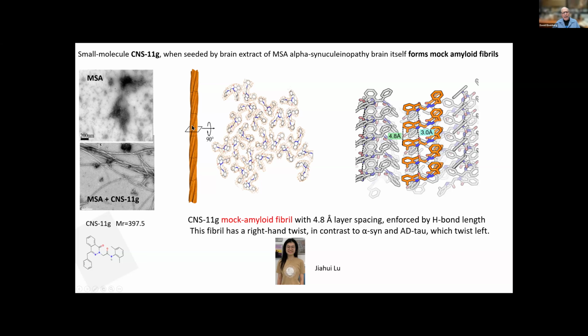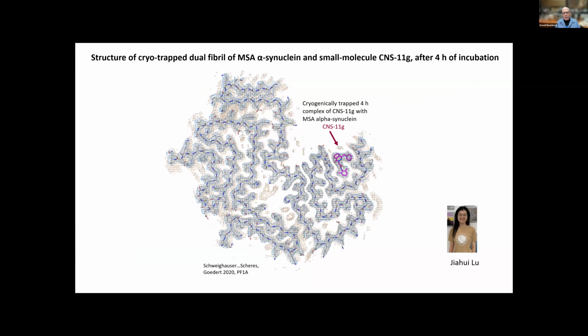Why does it have the same spacing of 4.8 angstroms per layer as amyloid fibers? The reason is it has an amide group, which you can see here. Here's the amide group, and it forms the same interlayer hydrogen bond that amyloid fibers do. So we call these mock amyloid fibers. So small molecule forms mock amyloid fibers.